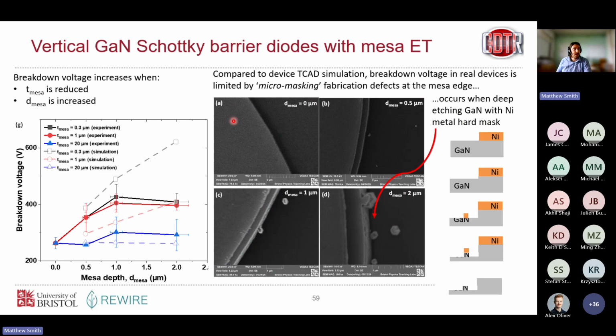So why is that? Well, we looked at these devices in SEM, and what we find is that for the deeper MESA structures, so 1 micron and 2 micron depths, we have these features around the edge of our MESAs here. So this is the anode contact, this is the MESA, and then this is the MESA floor. So as we go deeper to 1 and 2 micron depth, we can see these features here, and these are sharp, irregular features which are going to be electric field spikes in their own right. So they're what's going to cause this early breakdown.